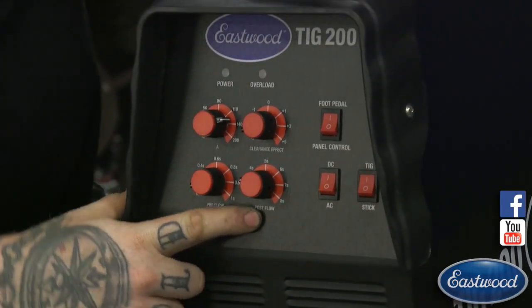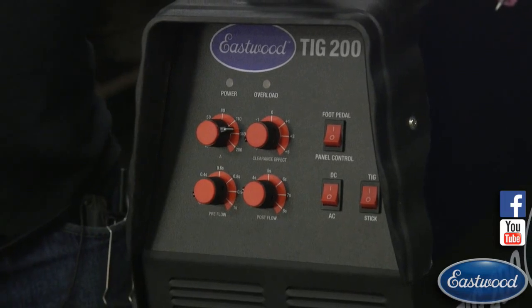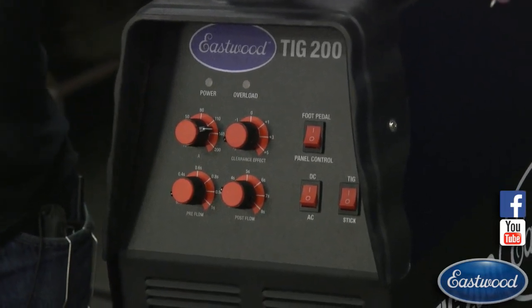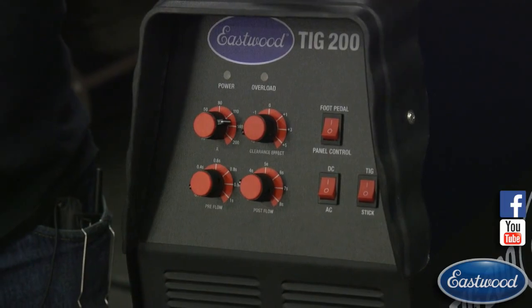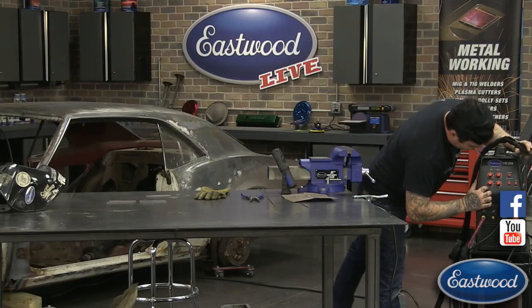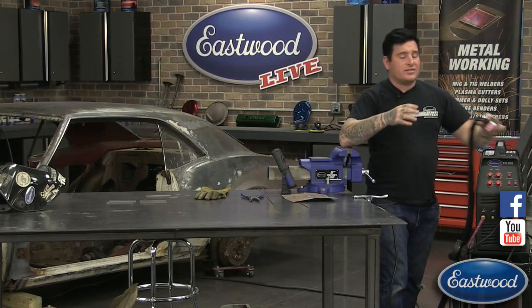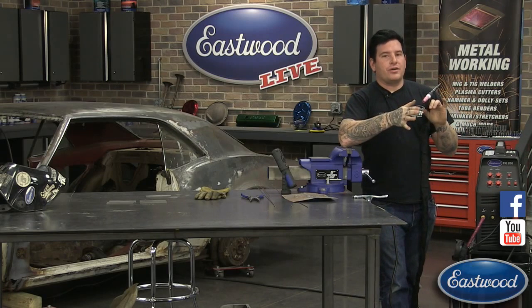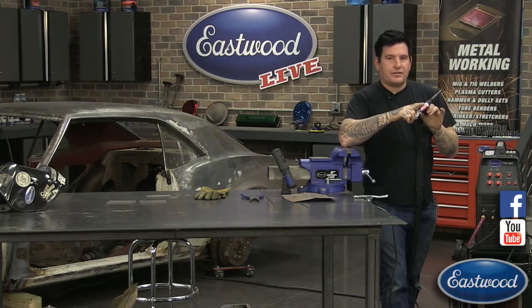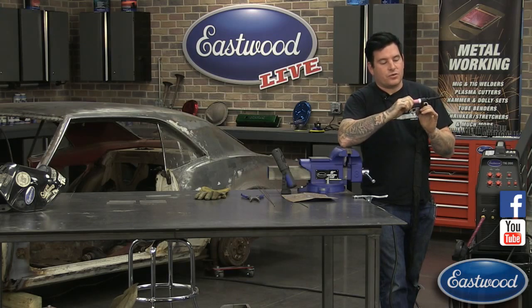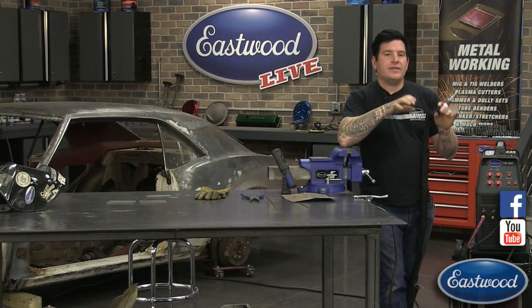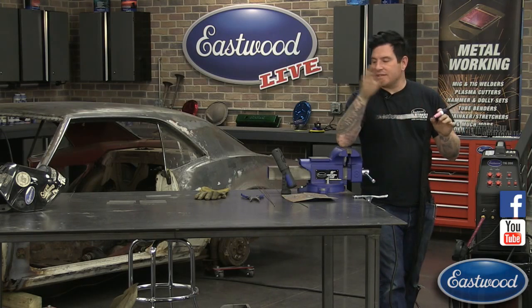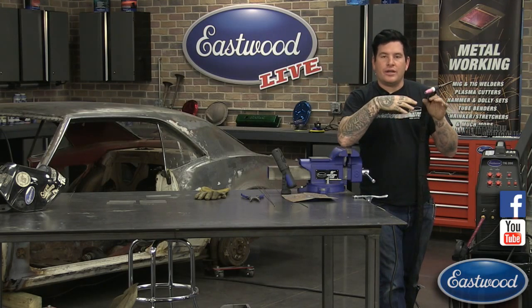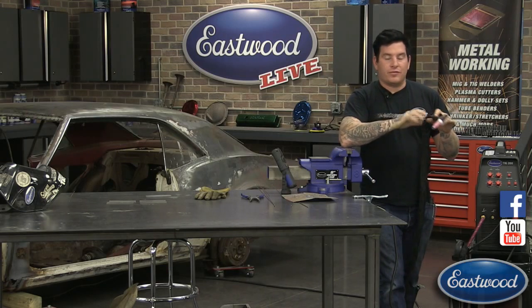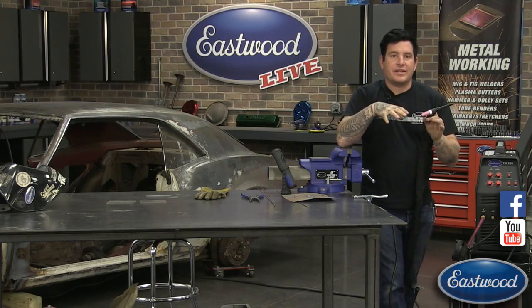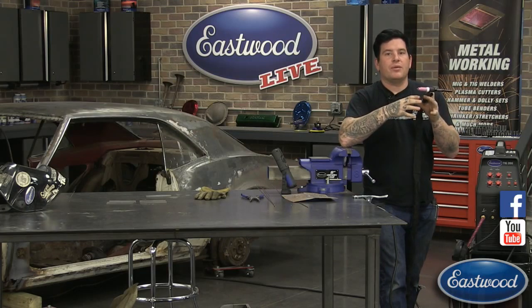On the bottom here, we have pre and post flow. When you're TIG welding, it's good to have as much, within reason, gas as possible to help keep the weld clean. The pre-flow is just like it sounds. It's gas that comes out before you initiate an arc. There's a couple reasons this is good. It can clean out the torch in case there's anything in the end of the torch here. It also gives you a head start. It gives you a little bit of shielding gas over your metal and your weld seam before you start welding. Before you even start an arc, you're putting a little bit of gas in that area to give you a little clean bubble to work in.